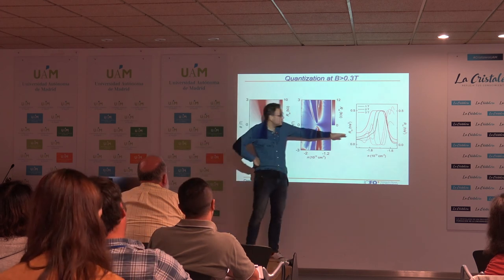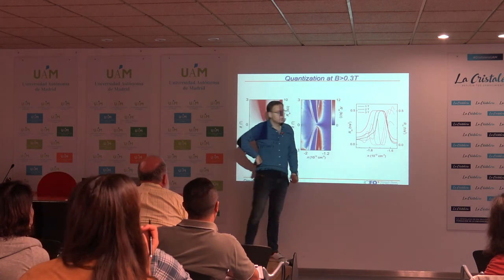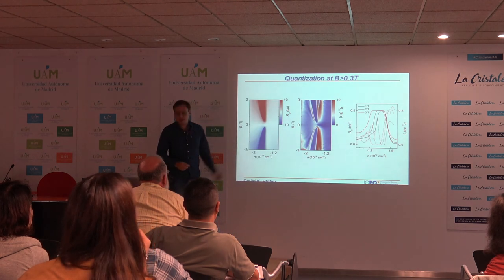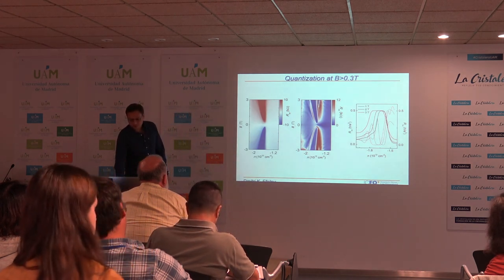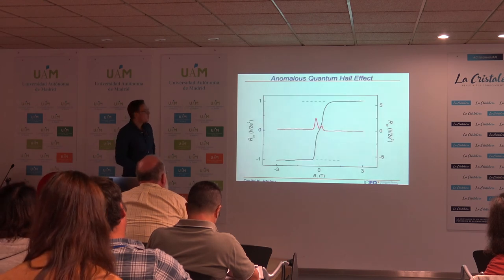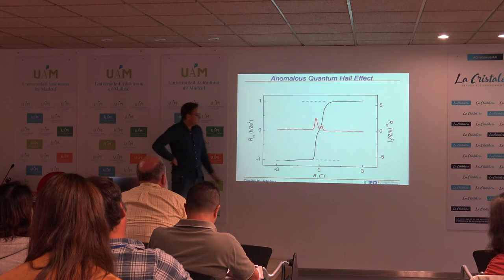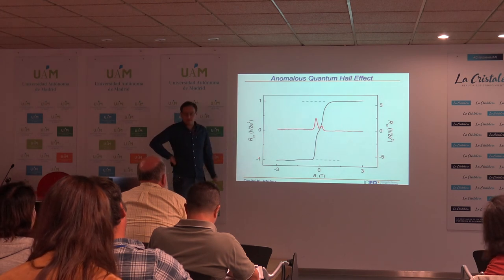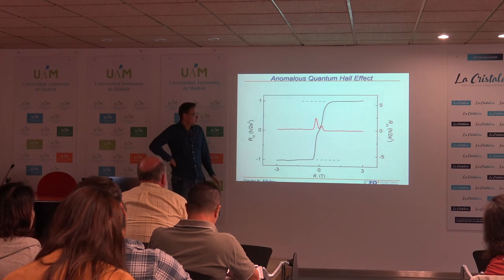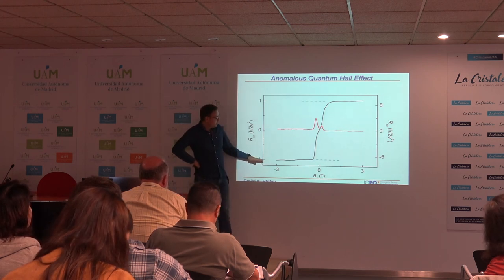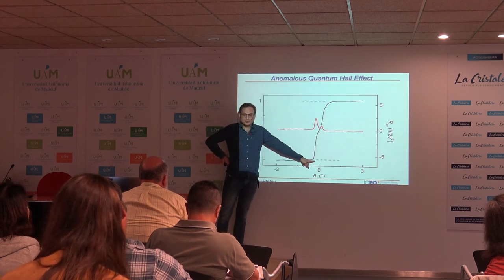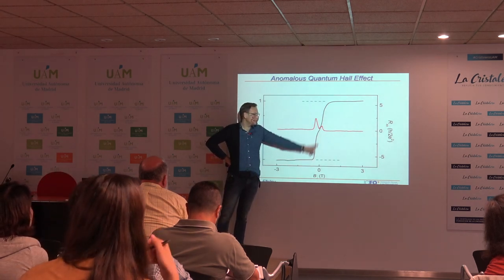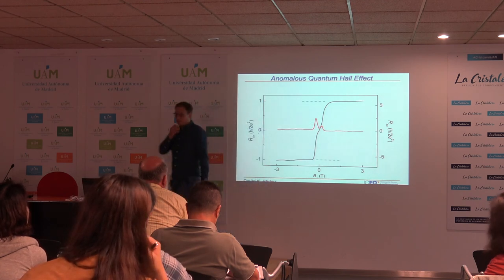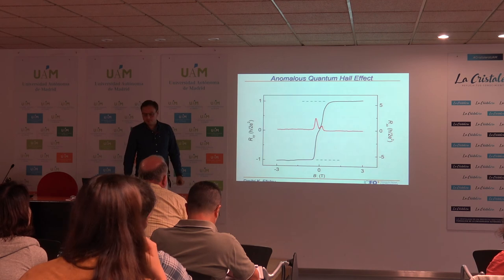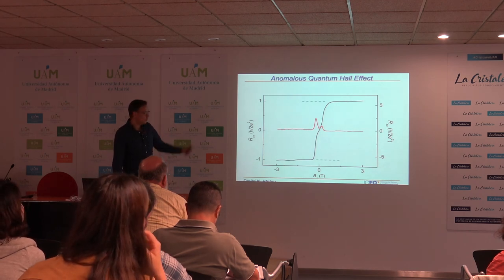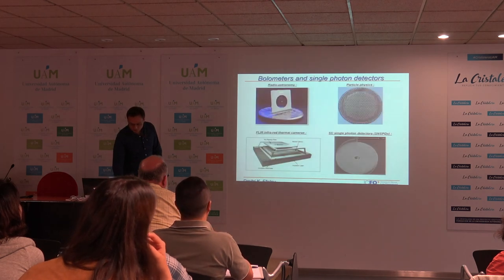These are traces which we can take, so we really get perfect quantization in some of these states originating at magnetic fields of around 0.3 tesla. If we take a line cut of this as a function of magnetic field, we recover a very similar feature to what was observed by the UCSB group: by sweeping the magnetic field, we get perfect quantization almost to zero, which then flips sign when we transition the magnetic field above zero. With this, I want to wrap up.